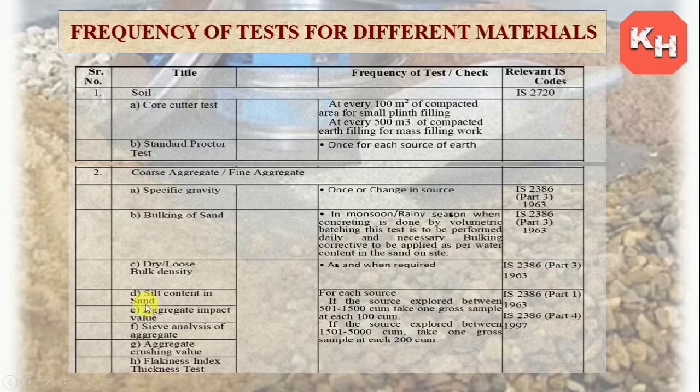1963. Silt content in sand. Silt content in sand is done for each source. Whenever we bring sand from any source, for each source we need to take this silt content test. If the source explored is between 501 and 1500 cubic meter, take one grab sample at each 100 cubic meter, and if the source explored is between 1500 and up to 5000 cubic meter, then take one grab sample for each 200 cubic meter. Remember this. This is as per IS 2386, Part 1, 1963, and IS 2386, Part 4,